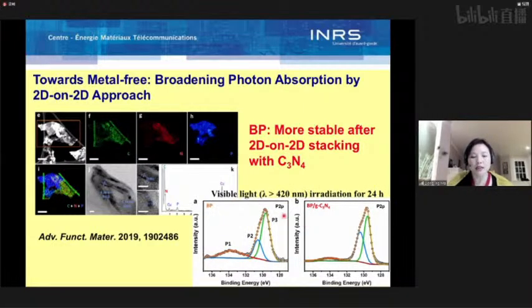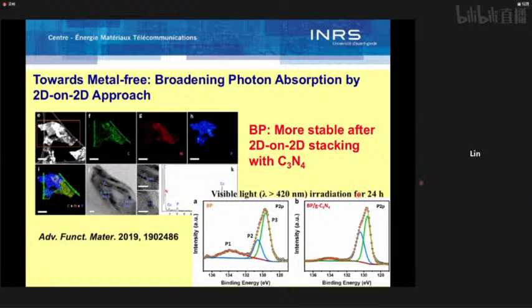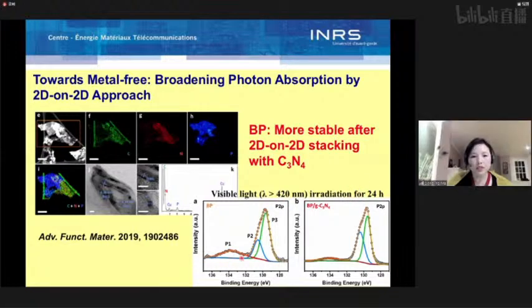So here you can see that under visible light, longer than 420 nanometer, irradiation for 24 hours, for pure BP, initially it doesn't have any P1 peak. This is related to the oxidized black phosphorus. So initially there's no peak, but after 24 hours under irradiation, we observed a dramatic increase of the P1 peak. But in clear contrast, for the nanohybrids after 24 hours, we only see a minimal increase in this peak. So it indicates the chemical stability of BP is largely increased due to this 2D on 2D approach.